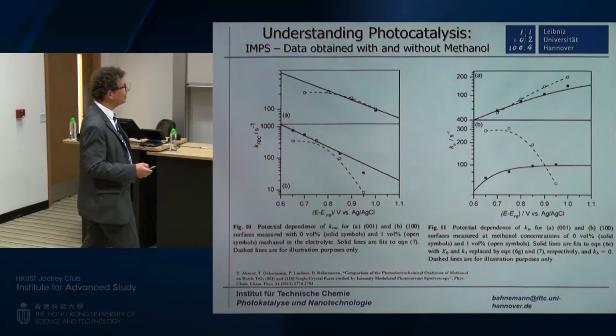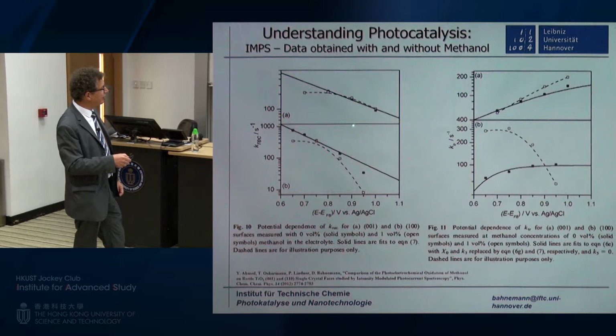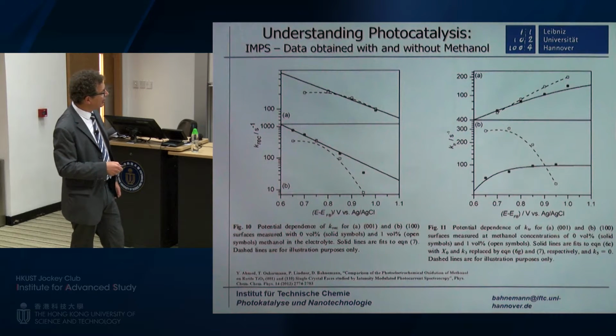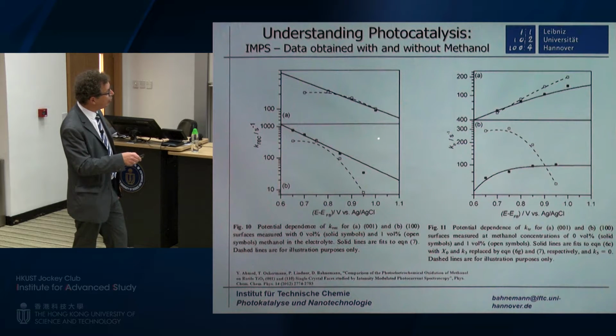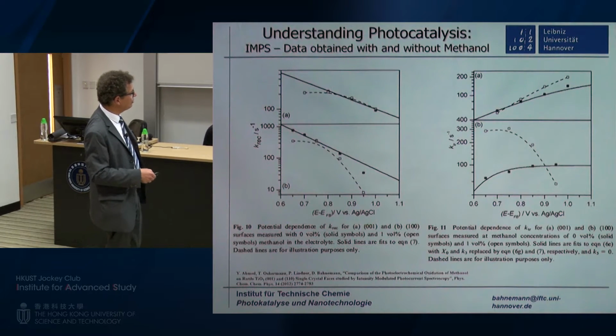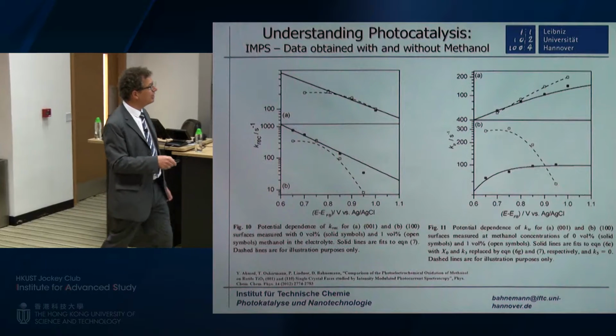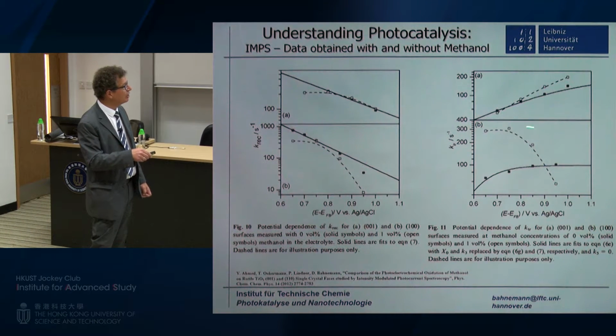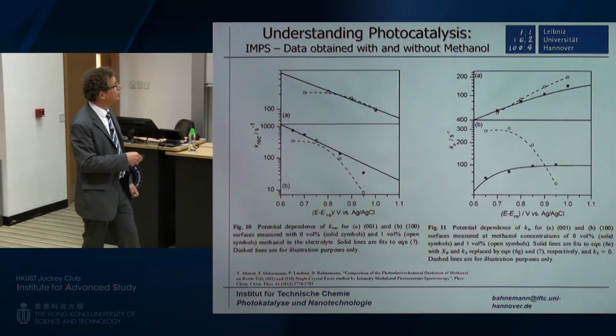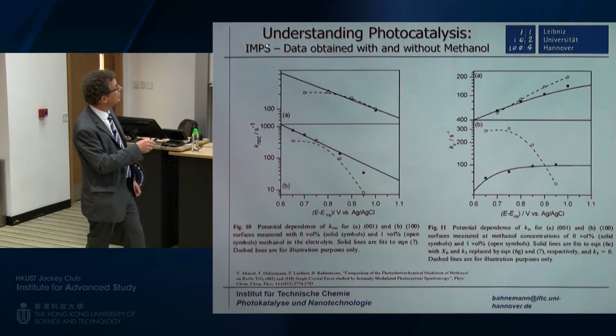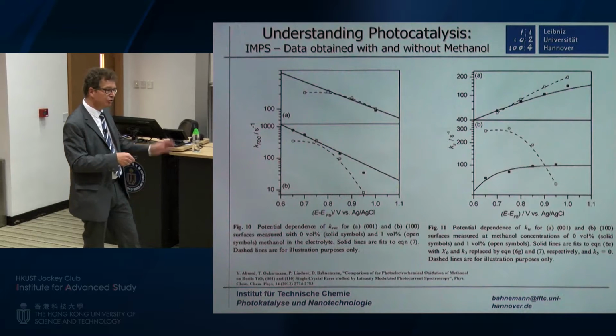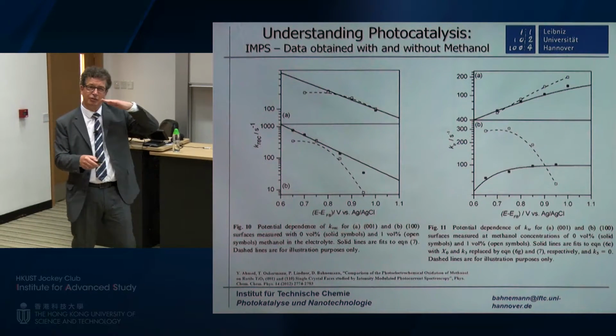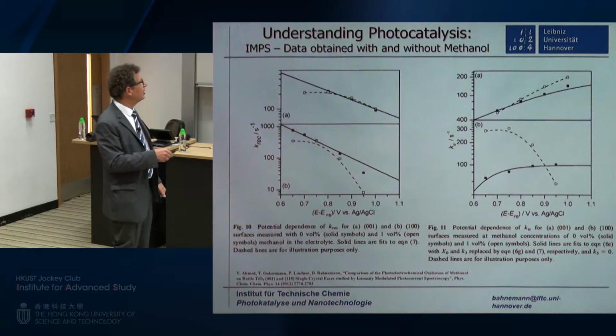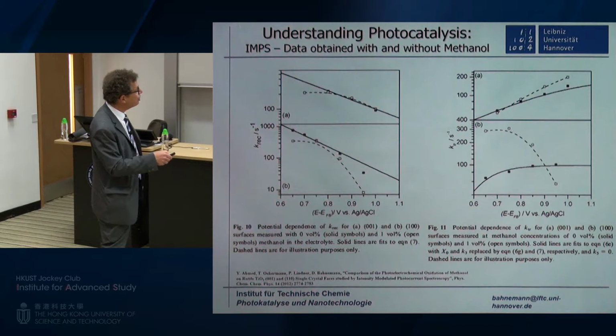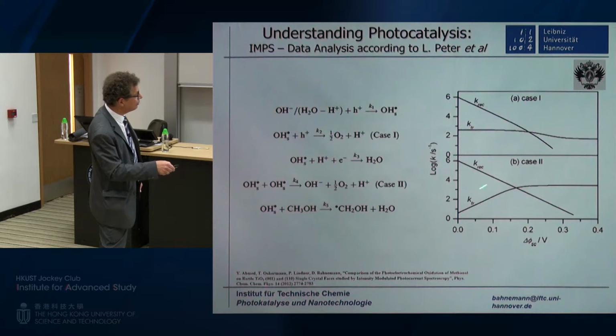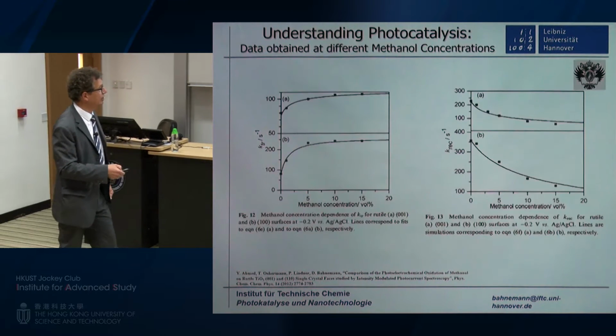So we did some experiments like this, and this is the potential again here, and you see the recombination rate constant decreases. This was done with rutile, and we also did it with anatase single crystals, and you see that the trapping rate constant is found to increase here. These are data from intensity modulated photocurrent spectroscopy, so you have a constant light which you then modulate, and these are the data you are getting. So we are pretty sure that, going back to the cases, we are in case 2 in our system.